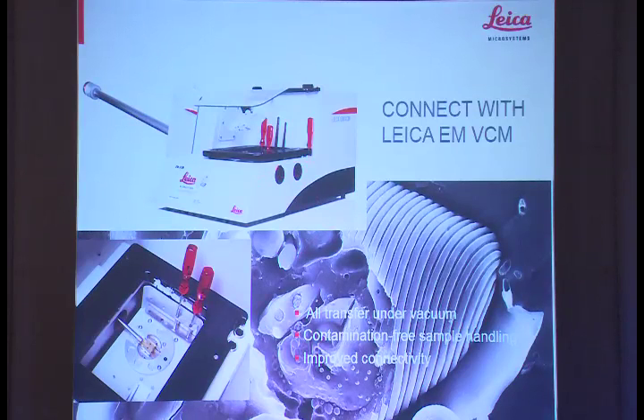These ports on the side allow us to move to the Cryo TEM as well. So here is our dock, which fits onto a Cryo SEM and onto our coaters. So we can come from a Cryo SEM or FIB, for example. If you've been doing some FIB techniques, you may have a lamella to carry over. You can take your lamella from here into the chamber and link onto here through to the Cryo TEM holder and off to the Cryo TEM. So you have a link through where you can have a contamination-free movement of sample.